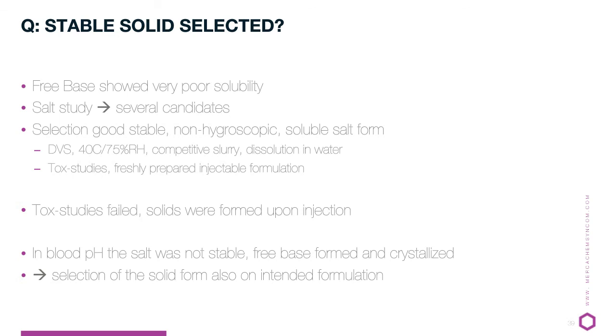We did stability tests, DVS, hygroscopicity, competitive slurry, and we looked at dissolution in water, and in the end this form was selected. In the tox studies, we decided to go with a freshly prepared injectable, and these studies failed. There were issues that solids were formed when injected.